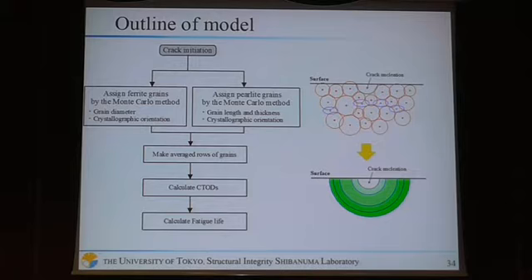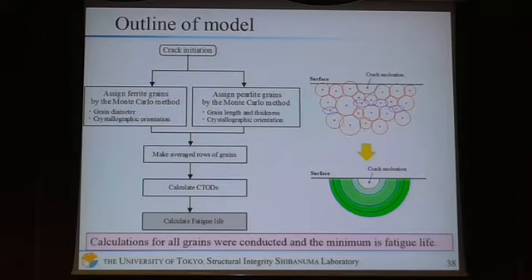After crack initiation, this model considers crack propagation. First, grains are filled by the Monte Carlo method. Next, these grains are transformed into grain rows. By this process, this model can regard the two-dimensional arrangement of grains as one-dimensional. Next, this model calculates CTODs and calculates fatigue life. Calculation for all grains is conducted, and the minimum is the fatigue life.